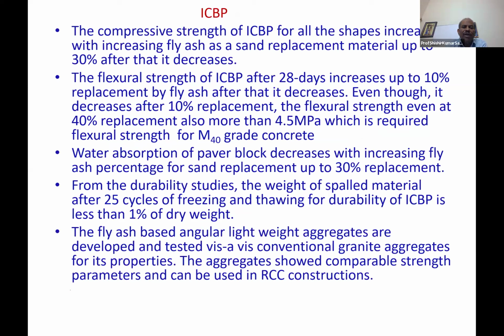ICBP: the compressive strength of ICBP increases with the increasing fly ash as a sand replacement material up to 30%. After that, it decreases. The flexural strength of ICBP after 28 days increases up to a certain replacement of fly ash. After that, it decreases, though only up to 10%. The flexural strength at 40% replacement is also more than 4.5 MPa, which is the required flexural strength for M40 grade concrete. So it can be used for pavement material. Water absorption of paver blocks decreases with increase of fly ash percentage for sand replacement up to 30%.